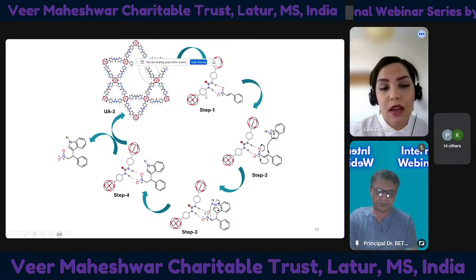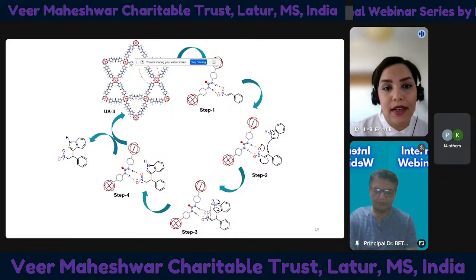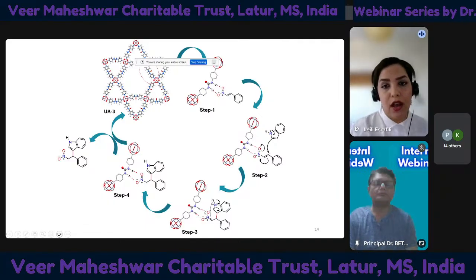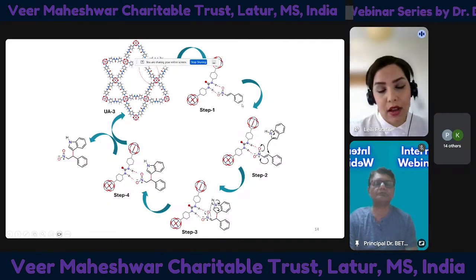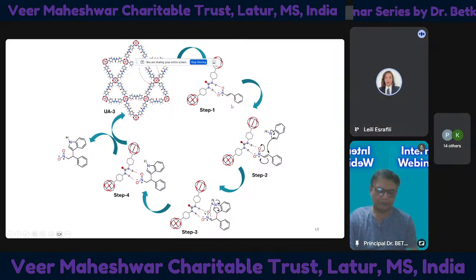So these are one of the linkers coming from this large pore. As you can see, it consists of hydrogen bond donors. Beta-nitrostyrene enters the pore and interacts with the hydrogen bond donor site. And as you can see, 2-point hydrogen bonding activates the nitro group.